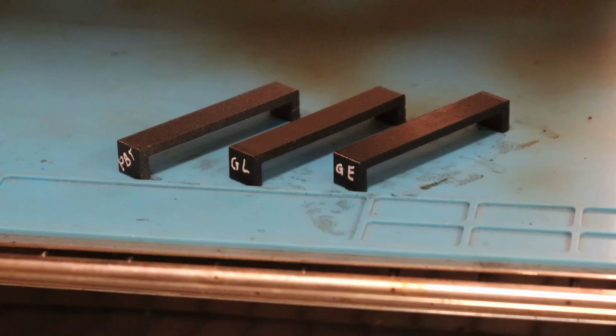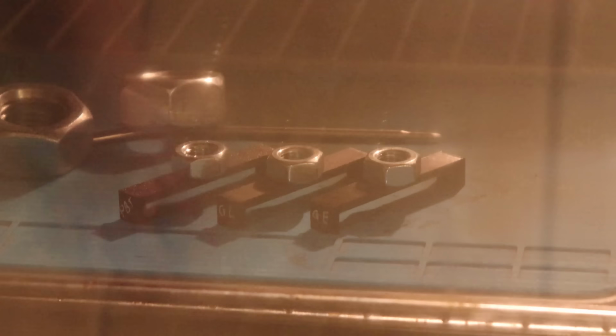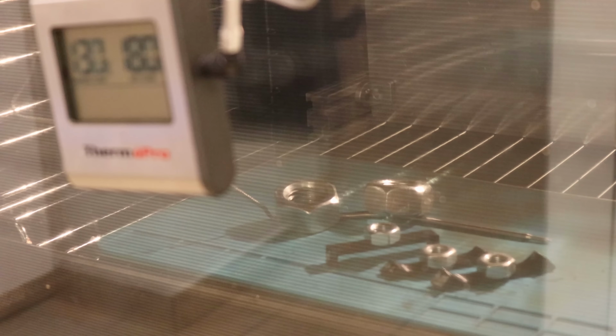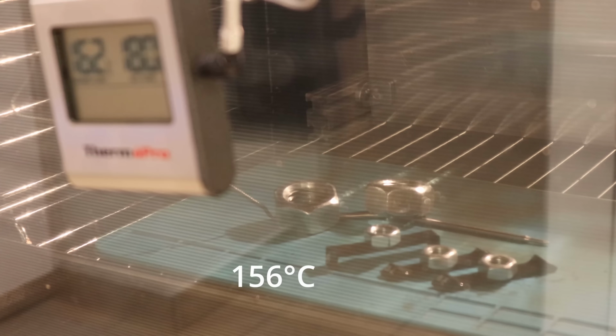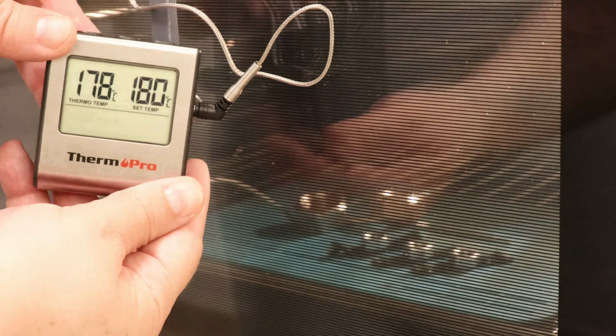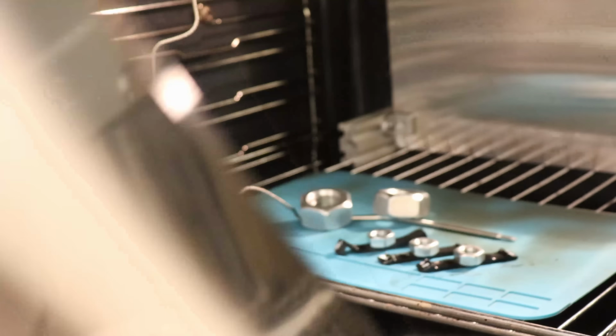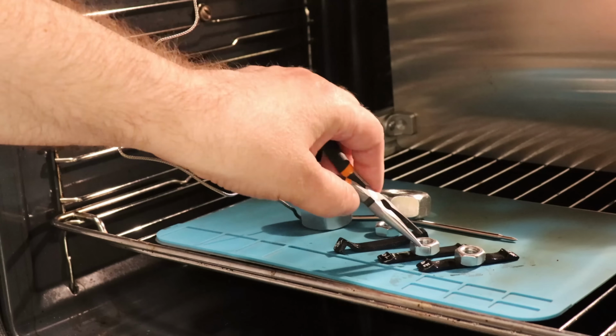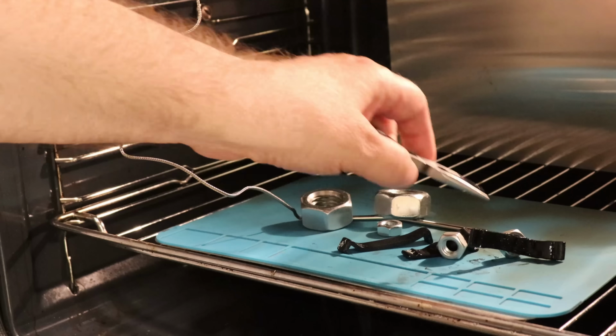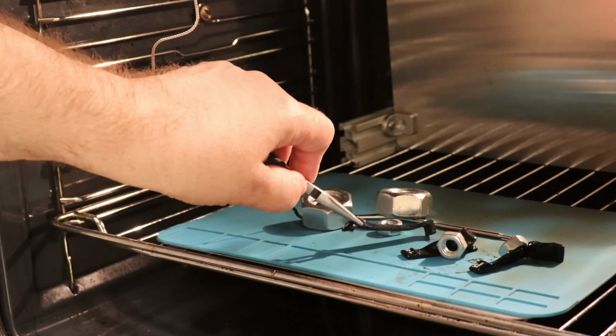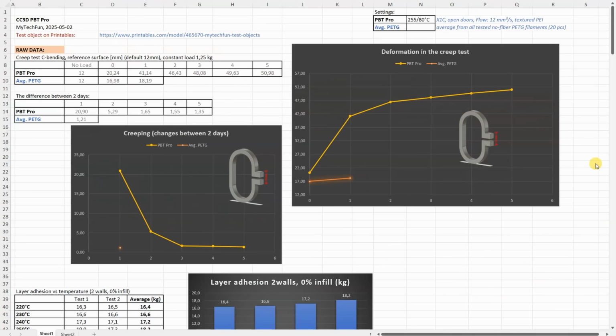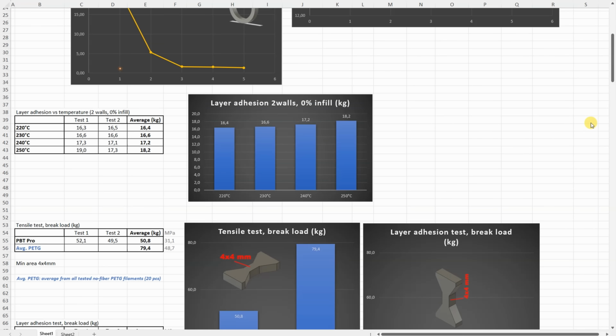Temperature test in the oven, and this one is from the PBT material. An M10 nut as a small load. And I want to record the temperature of the first deformation. The other two are graphene filaments, PLA and PETG, and on this PBT I noticed the first deformation only at 156 degrees Celsius. I stopped the experiment at 178 and until then it had completely deformed. And our results one more time without any additional comments.